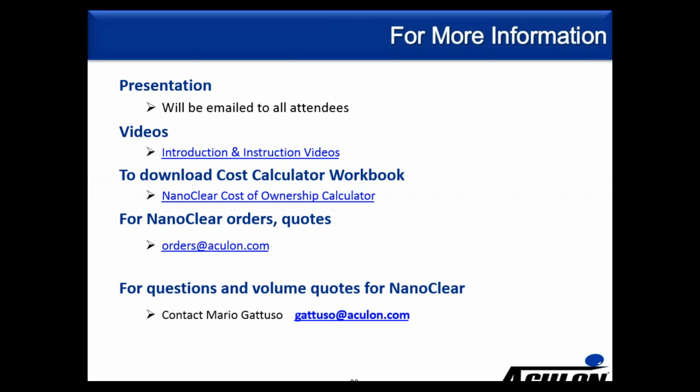Next question is, how many stencil washing cycles can the coating withstand? And that's a great question. So that depends on the cleaner that you're using. If you are using a non-aggressive wash cleaner, then the wash will not destroy the NanoClear. If you're using an aggressive or a high pH cleaner, then you could potentially have issues. And then how many prints and wipes can the coating withstand? Again, that is based on the type of cleaner you're using and the type of under stencil wipe. If you're using an aggressive cleaner and an aggressive under stencil wipe, then you might have longevity issues. You may have to reapply it after 5,000 to 10,000 wipes, or prints, I should say. But if you're using a non-aggressive cleaner and a non-aggressive wipe, then you're not going to see issues, and you should potentially hope to get a lifetime of treatment out of that treatment on your stencil, up to 25,000, 50,000 prints.